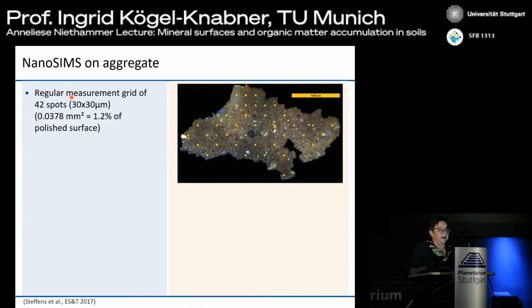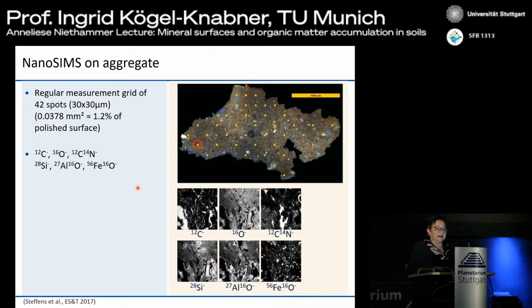And we made a regular grid. These are the yellow spots that you see here, 42 spots. The spots are not to scale, of course, but with these 42 spots we covered 1.2% of the polished surface of this aggregate. And we analyzed it for carbon, oxygen, nitrogen, Si, aluminum, and iron. So organic matter and minerals like we always do. But in this case, it's one aggregate.